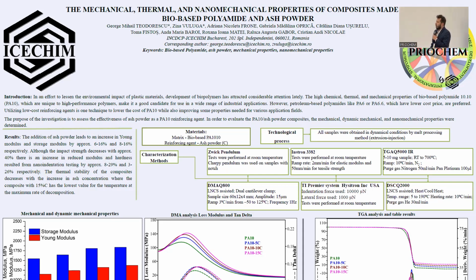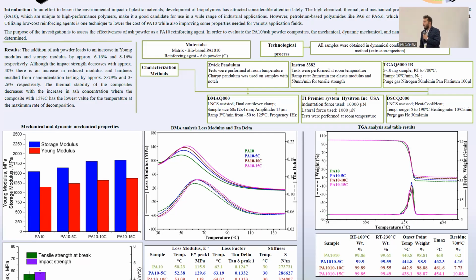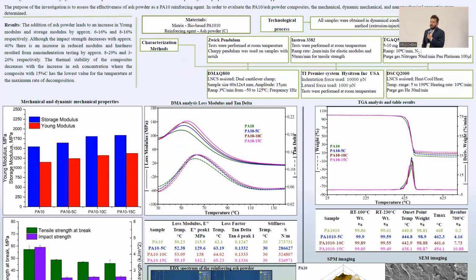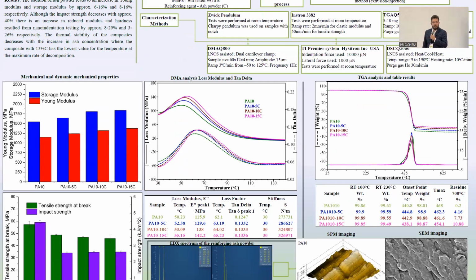These two materials were processed in dynamic conditions through melt processing methods such as extrusion and injection molding, and were characterized by mechanical analysis, dynamic mechanical analysis, thermal and nanomechanical analysis. And from the viewpoint of mechanical analysis, the rigidity of polyamide 1010 is increased with the addition of ash powder up to 16% at the maximum concentration of ash that we added.